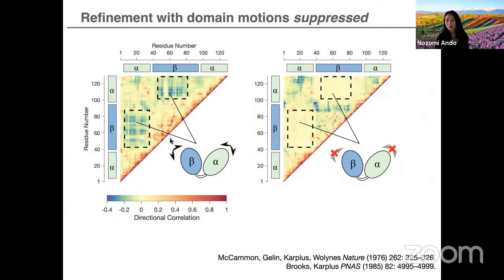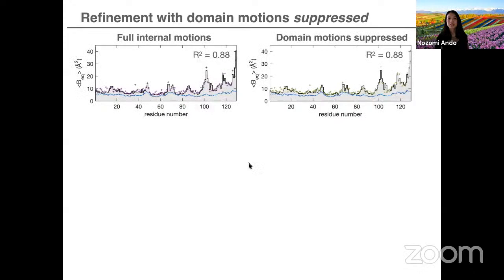But we wanted to wrap up this study by going back to the question that Peter Moore had posed, which is, what if you refine a model that's unrealistic? So we repeated this experiment, but this time didn't allow the domains to move relative to each other, while other parts of the molecule could. And what do we get from that? Here is the thing that's really scary: you can fit the B factors just fine with either of these models, to similar goodness of fits. So again, the B factors cannot distinguish a physical model from a non-physical model.